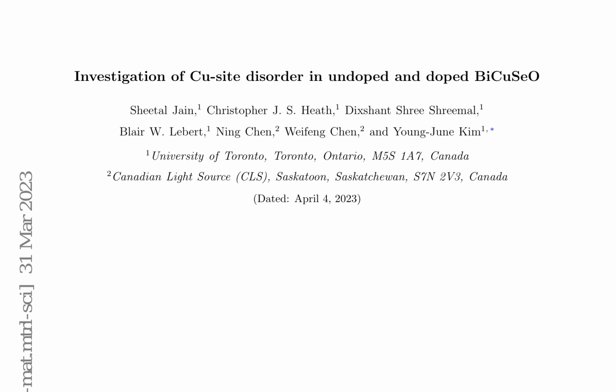XANES measurements on undoped and doped BiCuSeO samples exhibit a pronounced pre-edge feature in the Cu K-edge XANES spectra, indicative of Cu in a tetrahedral coordination environment. Notably, the intensity of this feature is significantly reduced in the doped samples, suggesting a decrease in the tetrahedral coordination of Cu ions. EXAFS results corroborate this observation, revealing a shortening of the Cu-Se bond length in the doped samples.